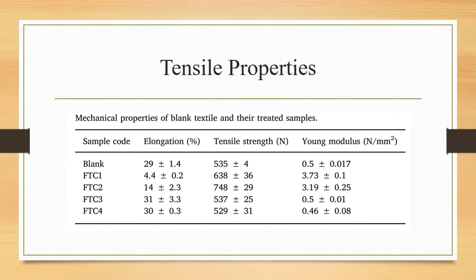However, when the smart coating layer was applied on the textile surface, the tensile strength was enhanced and achieved 638 Newton as indicated in the table for FTC1. In contrast, the elongation was reduced and the Young's modulus was enhanced. This might be due to the decoration of GR platelets on the textile fiber surface. The tensile strength in FTC2 was further enhanced with a whopping 748 Newton, which is roughly a 40% improvement. Also, the elongation was improved compared to FTC1. This, associated with a decrease in Young's modulus, reflects an increase in elasticity.